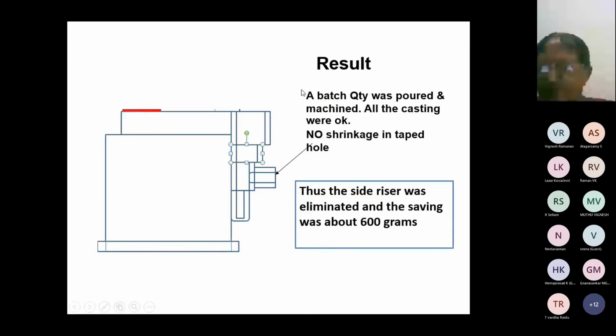A batch quantity was produced, and then the castings were okay. No shrinkage was there in this hole. So after machining, there was no blowhole in the thread. Thus, the side riser was eliminated by reducing the metal content, and the saving was about 600 grams. This is the first stage of improvement.